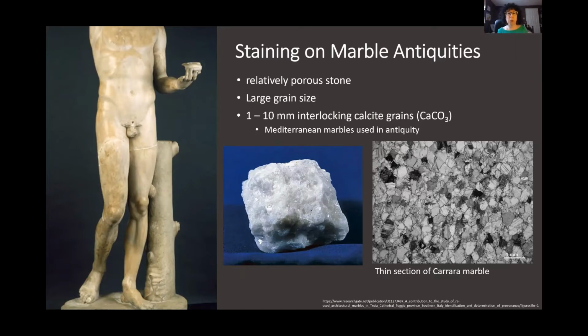In fact, if you have a broken piece of marble like I'm showing here, you can see how large the crystal grains are. They're actually visible to the naked eye. And this 1 to 10 millimeter grain size that you can see in the image on the right is particularly appropriate for the Mediterranean marbles that were used in antiquity. And in a way, this large grain size is wonderful, because that gives marble the magnificent translucency that made it so appealing to the sculptors of antiquity, but it's created some conservation problems for us down the road.